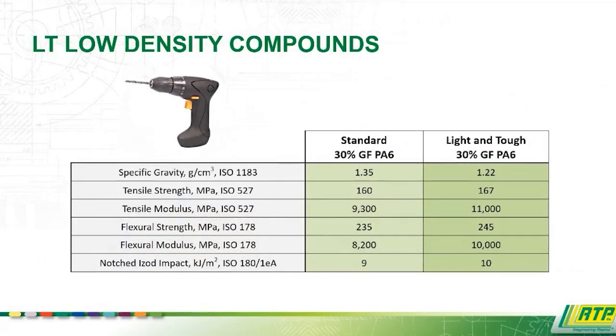So if we take a quick look at what those properties might look like, here's a standard 30% glass fiber nylon 6 and then a light and tough 30% glass fiber nylon 6. We can get around an 8 to 10% density reduction and basically maintain all the mechanical properties with a material that drops right in. There is a little bit of an added cost with the light and tough materials, but a lot of times the reduction in specific gravity offsets that cost increase. So you can about get a 1-to-1 price on a part with that reduced specific gravity and similar performance. Some interesting technology to consider.